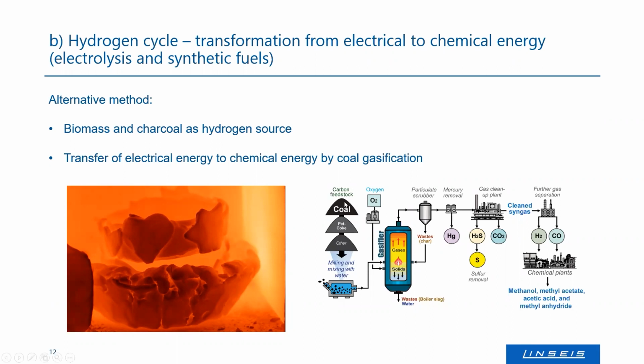So usually it goes like that. You have coal, you have biomass or others. You feed them into a gasifier, and the gasifier is simultaneously fed with oxygen and with water vapor. And then the water vapor reacts with the contained carbon of your biomass, and forms hydrogen and carbon monoxide. If you feed it with oxygen as well, it forms hydrogen and carbon dioxide. You can separate the gases that are created. You can use multiple filters, and out of that, you can get rid of sulfur. You can get rid of metals like quicksilver or other heavy metals like lead or whatever is contained in your material. And you can get clean syngas consisting of hydrogen and others.